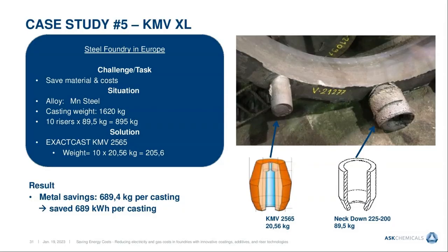In this example, we are talking again about a steel casting. This was a kind of manganese steel ring with 10 positions of risers consisting of neck down with 90 kilograms each. And our proposal to change into the KMV XL solution resulted in saving almost 700 kilograms per casting with our reduced volume risers. And in the end, the foundry was also able to save around 700 kilowatt-hours per casting.